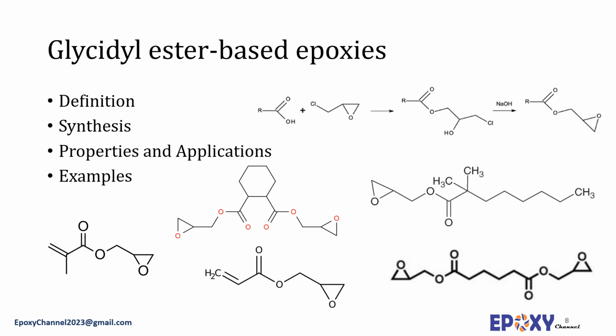1,2-cyclohexane dicarboxylic acid diglycidyl ester is one of the most well-known diglycidyl esters in the market. It is used as a high-temperature resistance coating for substrates such as metal and plastics. This product has been shown to be resistant to water vapor and the formation of hydroperoxides and peroxides, which can lead to degradation of the coating.